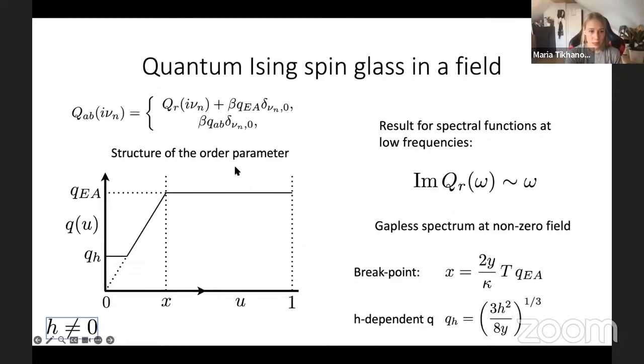All right, so the main result that we found is that in this specific model, first of all, there is a spin glass solution, there is a replica symmetry breaking solution, and also the spectral functions in this phase are all gapless. So that's interesting because there's no gap, even at non-zero field.